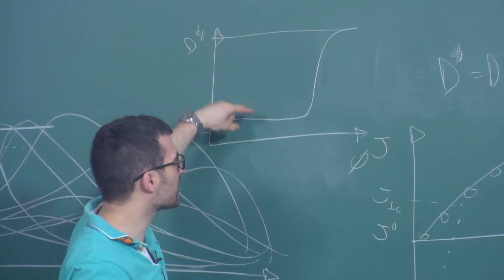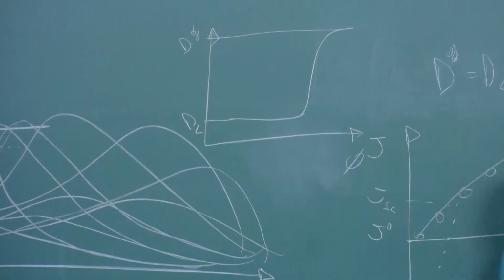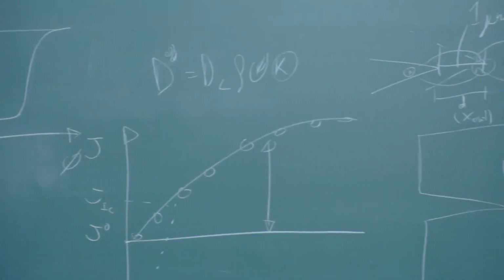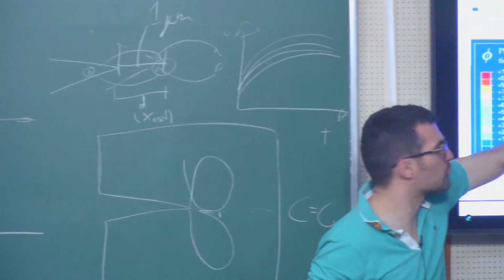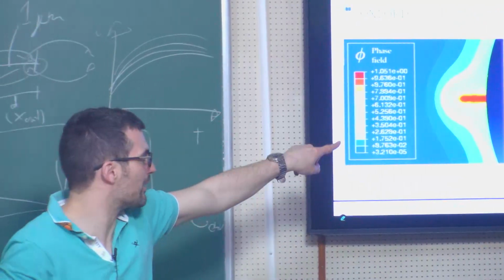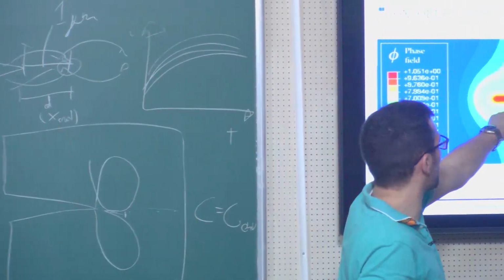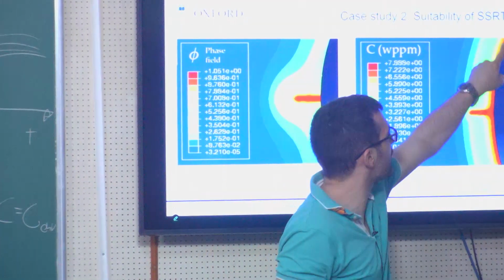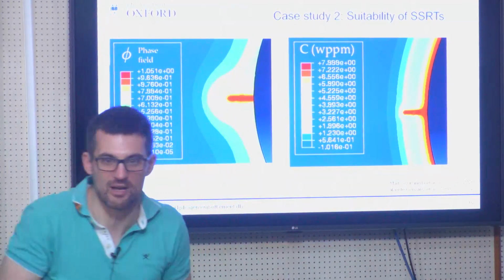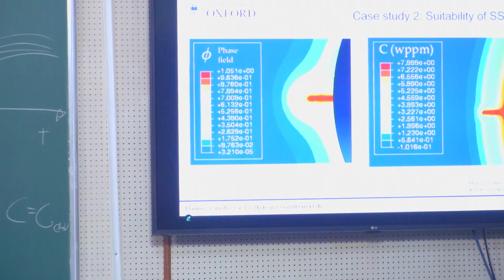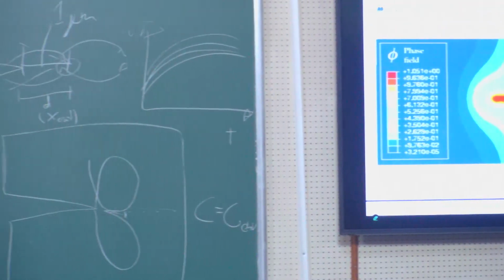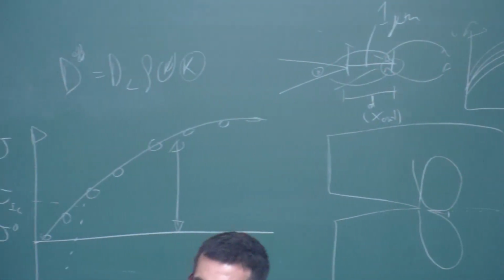And then when you do that, because basically the diffusivity is enhanced here, the hydrogen here will just go quickly, and you capture this kind of behavior. You capture what you want to see. You want to capture as the crack grows, the hydrogen from the environment immediately fills that gap. So you can do that with this type of expressions or with a penalty approach. But this one is much easier to implement, and it seems to work better. Yeah.